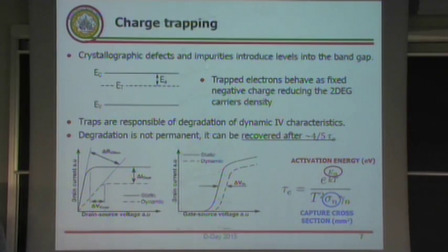However, despite these very promising performances, gallium nitride still has many open issues, and probably the most addressed is charge trapping. In fact, any crystallographic defect or impurity within the device structure creates an energy trap level, or a trap state, within the band gap of the semiconductor, which is characterized by an activation energy. That is the energy difference between the conduction band and the level of the defect.